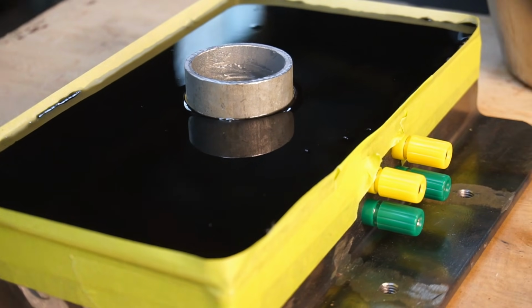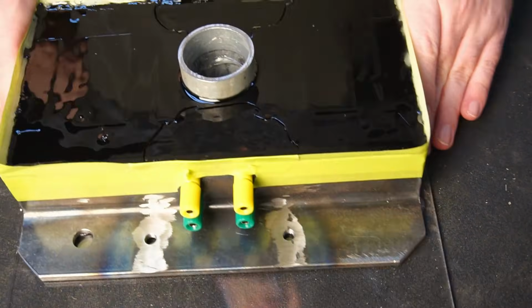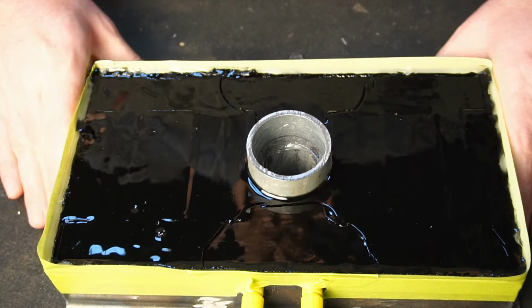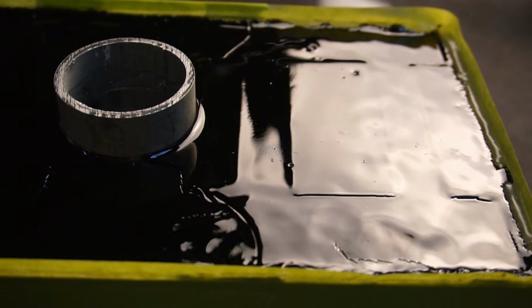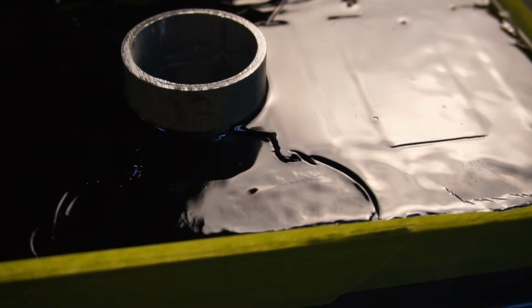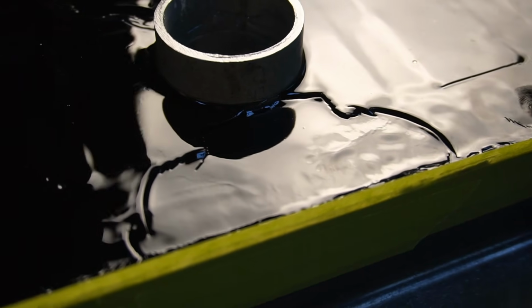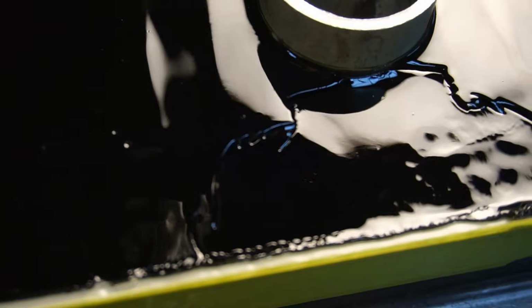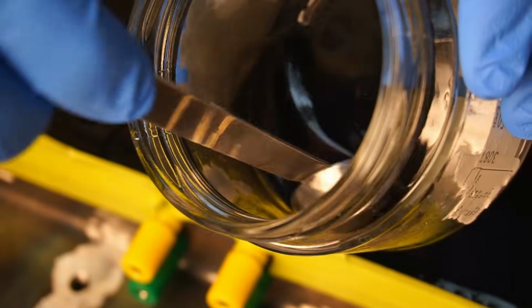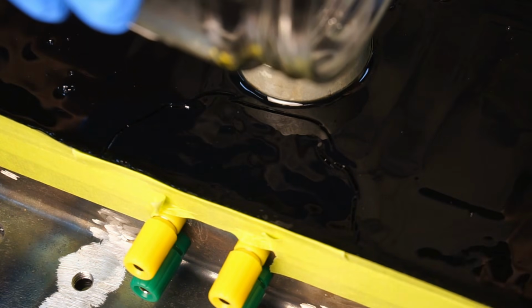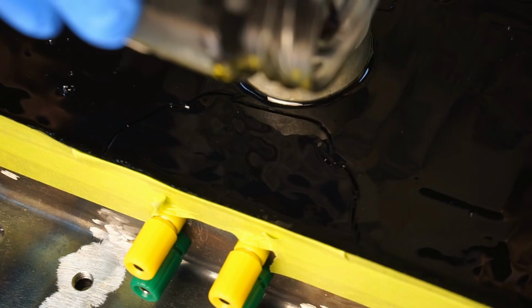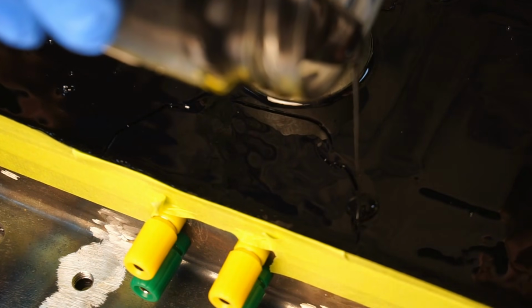I left it overnight and the next morning I was greeted with a couple of cracks in the resin. These cracks were likely due to the widely varying thickness of the resin and leading to uneven contraction as the resin cured. Fortunately, it's not a big deal to fix. I just mixed up a mini batch of resin and filled the cracks. The polyester resin I'm using bonds extremely well to itself even after curing.